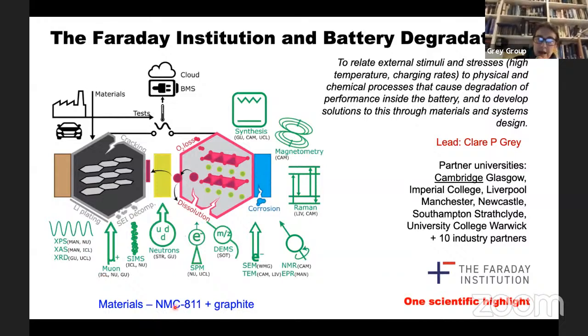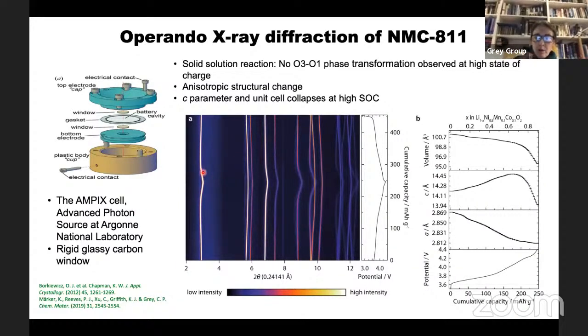And the material we're looking at is NMC, so nickel, manganese, cobalt 811, and graphite on the other side. My group, for example, uses NMR spectroscopy, obviously, but we also do SEM and TEM, and we do DEMS, which is a method of looking at gas evolution from batteries. We do some neutron diffraction and XPS and things like that. So I'll use a whole variety of different techniques to look at these systems. And this is just one example to give you a flavor of the sorts of things we do.